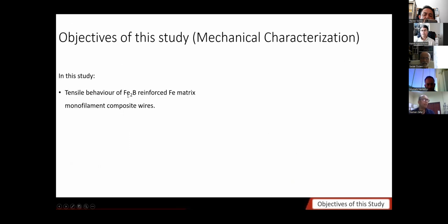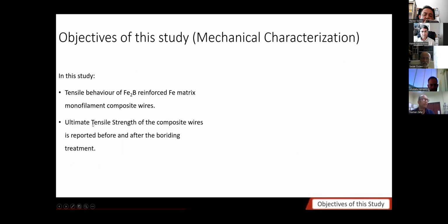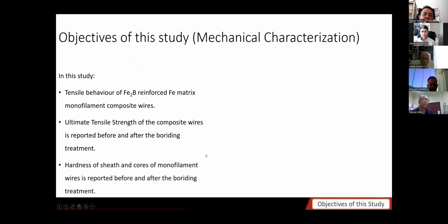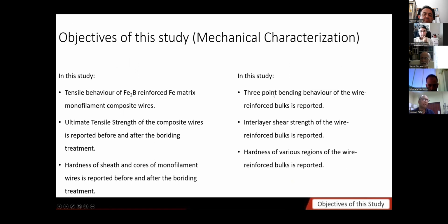The mechanical characterization is done by the tensile behavior of Fe2B reinforced composite wires, and the ultimate tensile strength of the wires is also reported, and the hardness of the sheath and the cores of wires is reported. All these mechanical studies are at the wire level, and then these studies are at the bulk level. We have used 3-point bending tests. Interlayer shear strength of the wire reinforced bulks is reported, and hardness of various regions in the wire reinforced bulks is also reported. So these are the mechanical characterization objectives of this study.